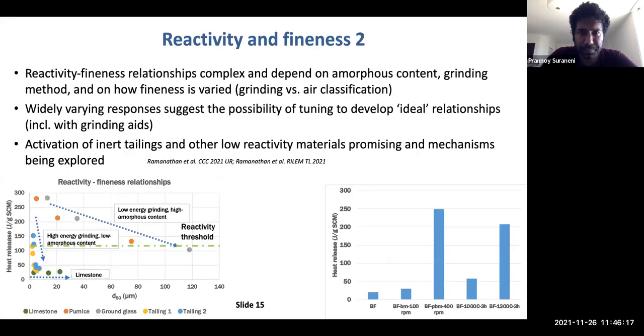Now, let's look at what happens when you start grinding materials. So when you grind materials, the grinding energy is really important. It's also important what material you're grinding. So this is a very busy graph, I apologize. But what we found was that first, if you take a material like limestone, it doesn't matter. You can grind it however you want. We did not see any change in the reactivity based on the grinding.